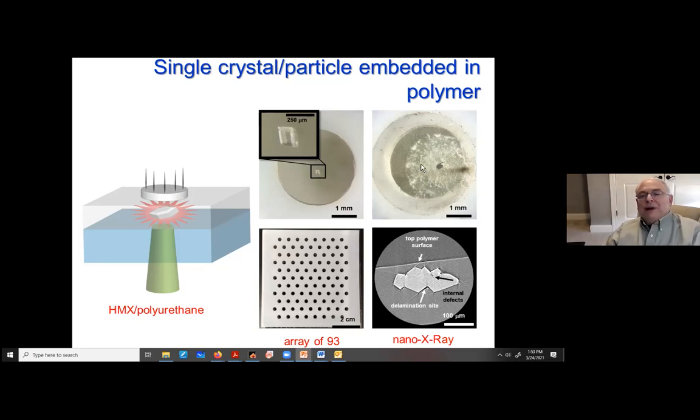Finally, we take a limited number of these over to our X-ray analytical facility, and we do an X-ray image of it. And here is a roughly 1 micron resolution X-ray image of a really funny looking HMX crystal that we have been using. And here's the top of the polymer. Here's where the flyer plate comes in and so on. Oh yeah, that's a little delamination. That's a little internal void. These are little pointy things. You know, there's a lot of funny structures here.